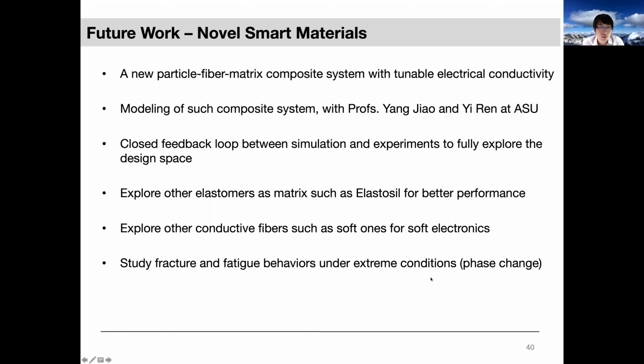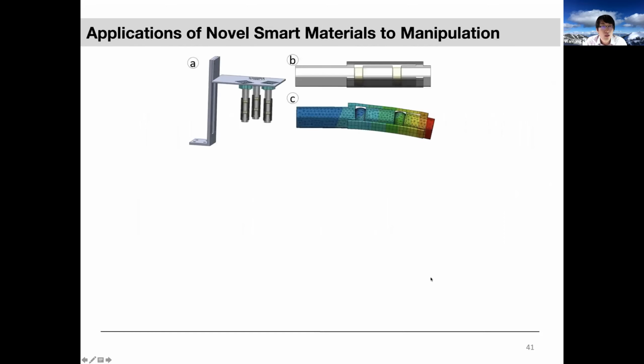We also want to change the elastomers. For example, PDMS is not an ideal elastomer, I would say, because of certain mechanical properties, especially for fracture and fatigue. We also want to explore other conductive fibers, such as soft ones, especially low melting point alloy. If we can make low melting point alloy fibers, the interaction between the fibers and the particles will be very intuitive to investigate. We would like to study the fracture and fatigue behaviors of these composites under extreme conditions, for example, during activation.